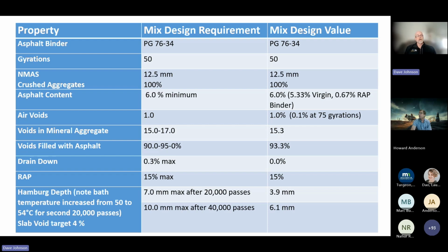But as we can see here, after 40,000 passes designed and built at 4% air voids and increasing that temperature by 4 degrees on the second 20,000, they had a grand total of only 6.1 millimeters of rutting.